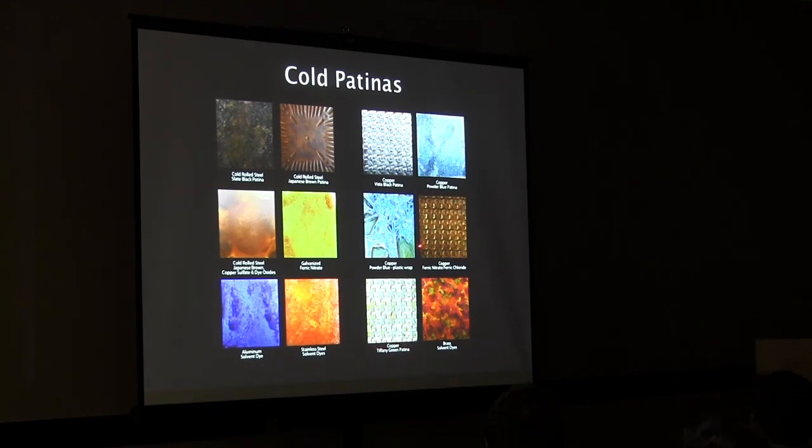Next one here, this is copper. I got Tiffany green, that's Tiffany's formula. I modified it slightly, but it's basically Tiffany's formula. I put the green on, let the green dry till it got the kind of mottled greens. Takes about an hour. Then I washed it under hot running water for about 2 minutes. You start getting oranges and yellows and browns. So it's a multi-patina. You can have different things with it depending on what you do with it. One is to wash it.